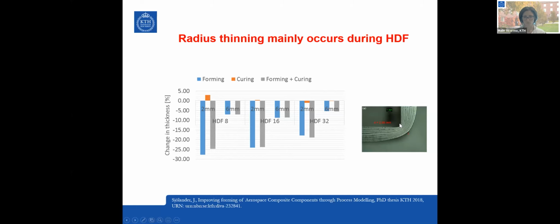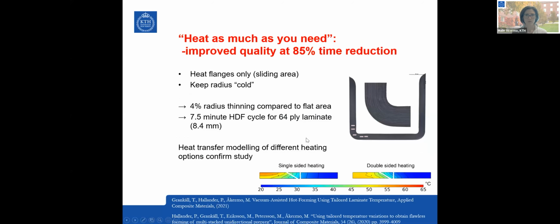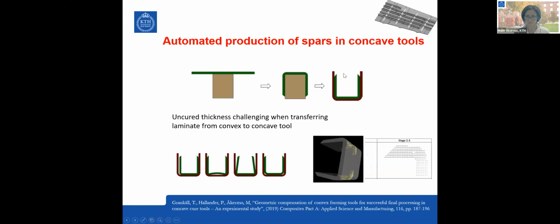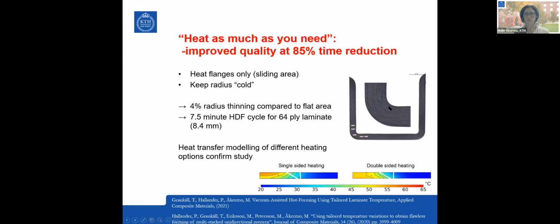So we started playing with temperature, trying to find the minimum temperature possible that could be formed without causing wrinkles in the flanges. Because if you have too low temperature while you form, there will not be any sliding in between the layers, and it will wrinkle. And this study has boiled down to a conclusion that for these kinds of beams that we are producing, you should actually only heat as much as you need, at the area where you need it. So heat the flanges only, and if we then keep the radius cold, at room temperature or even lower, we can actually maintain the thickness of the radius.